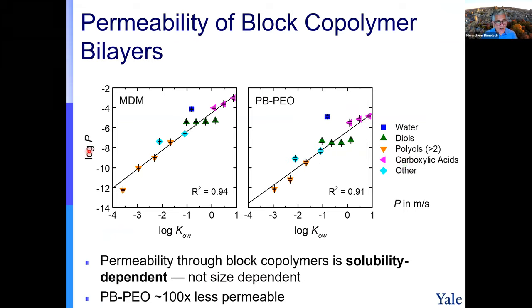On the other hand, we correlated the permeability to the octanol-water partitioning coefficient, which tells you how polar the molecule is, or how likely it is to partition into an oily phase. The larger the KOW, the more it can partition into this oily phase. And you see that we found a beautiful correlation of permeability to log KOW. As the hydrophobicity increases, for both the tri-block and the di-block copolymer vesicles, we see that permeability through the block copolymer is solubility dependent. The molecules solubilize, partition into this bilayer, and then diffuse through the bilayer.